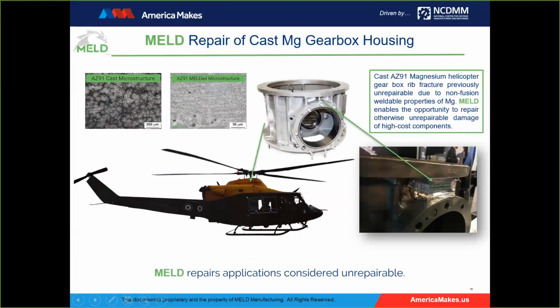But here's an example to hit home on the technology in terms of addressing unfriendly materials. Here's a cast magnesium helicopter transmission gearbox. That rib is prone to failure. At the moment it cracks, it becomes an $80,000 piece of scrap material because magnesium is unweldable. But it's not unmeldable. We used the same cast AZ91 magnesium. We machined down the rest of that rib. We deposited a number of layers, that's a 1/2 inch track here, of the same material.